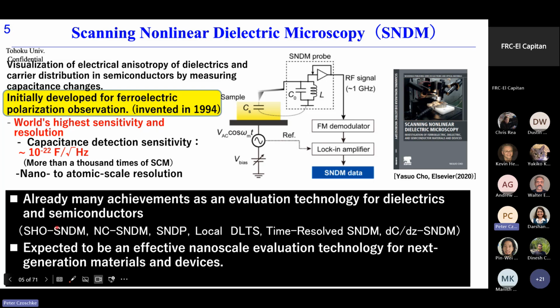and detect the higher harmonics up to the 12th harmonics, or non-contact SNDM and scanning nonlinear dielectric potentiometry, which can measure the atomic dipole moment of the sample surface with atomic resolution. And when we measure the semiconductor MOS, metal oxide semiconductor interface, we can use the local deep level transient spectroscopy method. It is a modification pattern of the SNDM. And now we also developed a digital type SNDM named time resolved SNDM and so on. So now it is expected to be an effective nanoscale evaluation technology for next generation materials and devices.